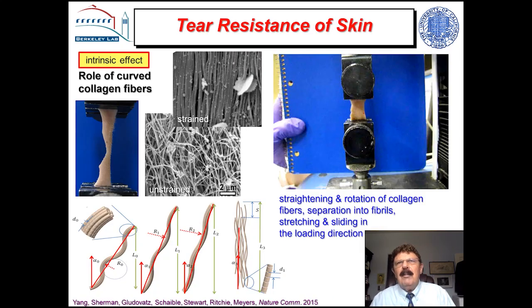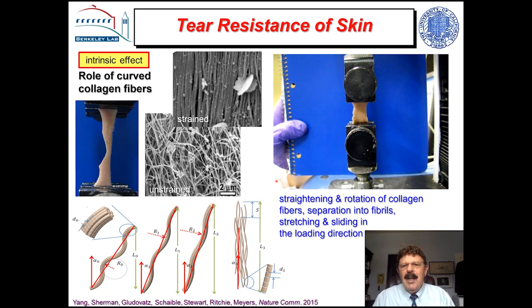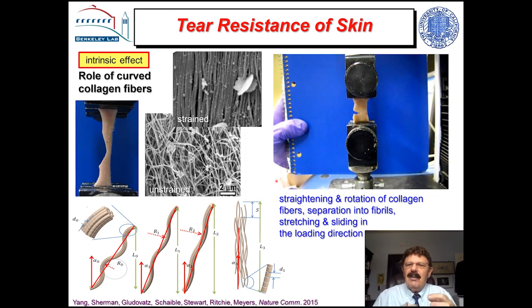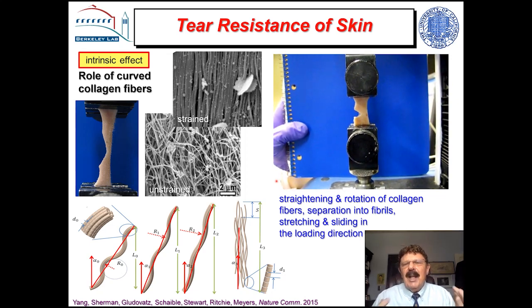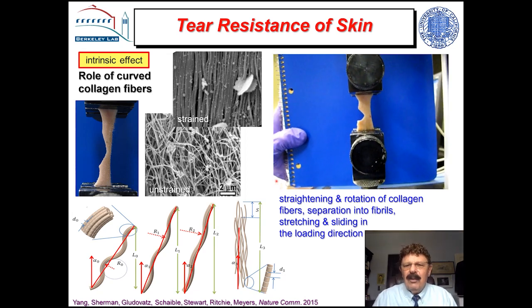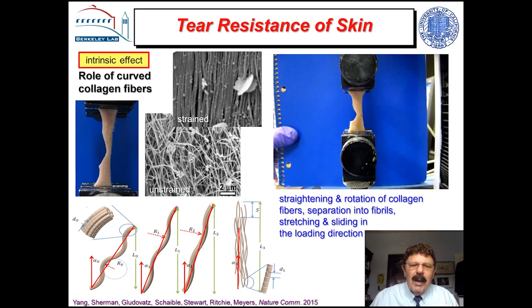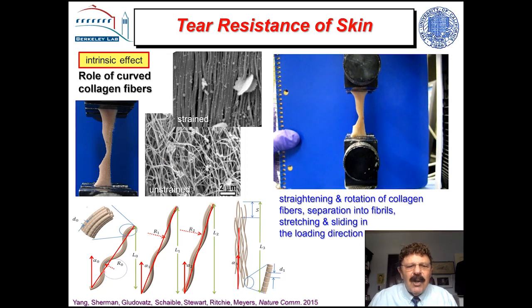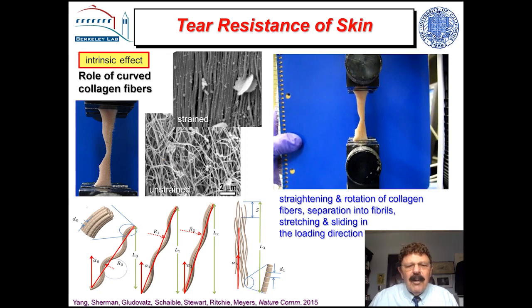Now, if we look at other biological materials, some of them are intrinsically toughened. Skin is a good example. It's collagen again, but non-mineralized collagen, just pure collagenous material. Skin is virtually impossible to actually break. You do a tear test on it and it just won't break. It generates blunt cracks and so forth. Now, how does that work? Well, it consists of a tangled mass of collagen. These collagen fibers are very twisted and curved.